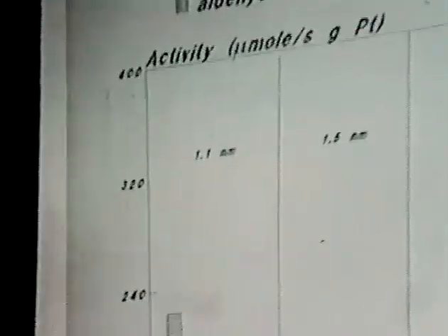As you can see in these other samples, the high temperature reduced samples tend to have somewhat higher selectivities to crotyl alcohol. Again, 37% is the highest. We see in some cases also the formation of butanol, complete hydrogenation, and that appears to be almost certainly the complete hydrogenation of the crotyl alcohol to go on to butanol. So it's very complicated. We want to stop with somewhat of an intermediate product, and of course we can do so with varying degrees of success.